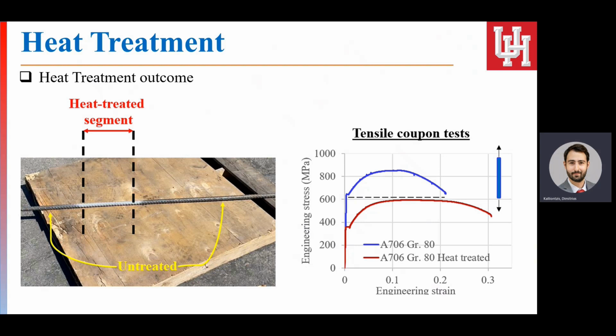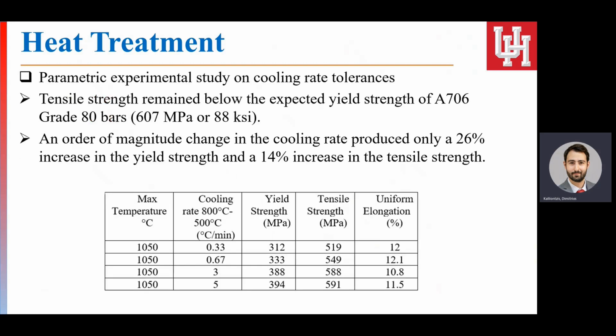And then here you see experimental results of engineering stress versus engineering strain of the heat treated and untreated section. So you see that the protocol that we developed is effective in the sense that it meets the requirements that we set for the bar. We also conducted a parametric experimental study of the cooling rate tolerances, specifically because we wanted to see what type of quality control we need to consider when this method is implemented in practice.